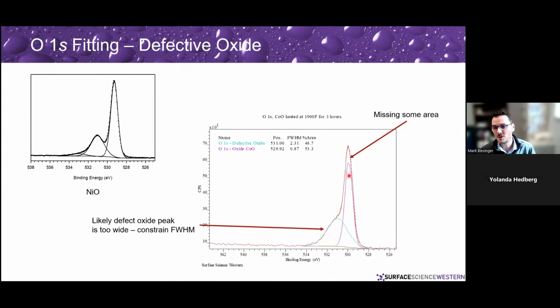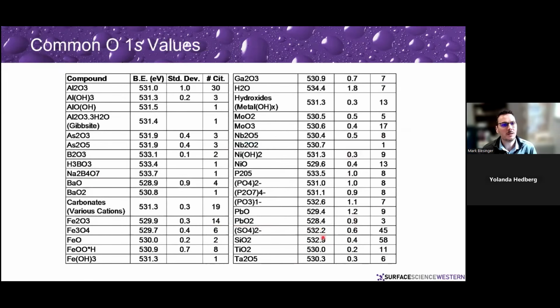You know, this peak should really fit this envelope very closely. And then this peak should be narrower so that it is more accurate about how much of that defective oxide or hydroxide is actually present. So those are some pitfalls that you can get into.